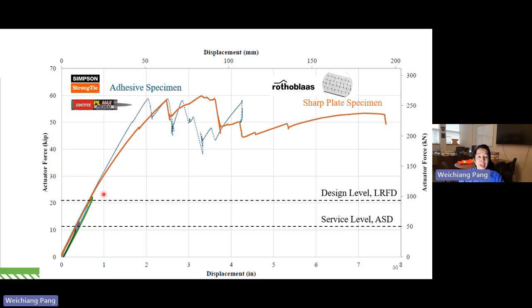So what we notice, as I mentioned, is that the initial stiffness of both specimens is almost identical for all practical reasons. However, you can argue the sharp metal is more ductile. At least this specimen shows more ductility. We were able to push it further without seeing it structurally compromised. The adhesive one is more brittle, if you will. However, the peak load, the peak strength, is almost the same.